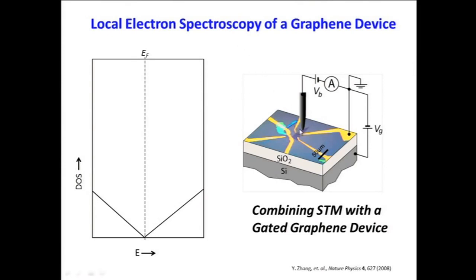What we expected to see when we did this experiment a few years ago was a V in the local density of states, in the dI/dV, because the local density of states of a material often mimics the total density of states, which is linear for graphene. And there's the Dirac point. That's what we expected to see. But when we did the experiment, that's not what we saw. In fact, we saw something that looked kind of different. Here I show you the data, what we actually saw.